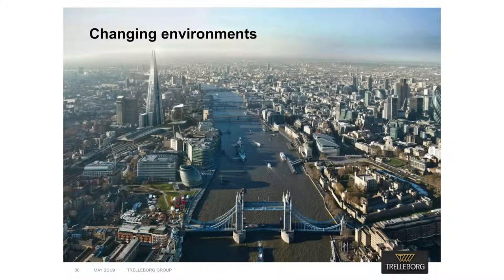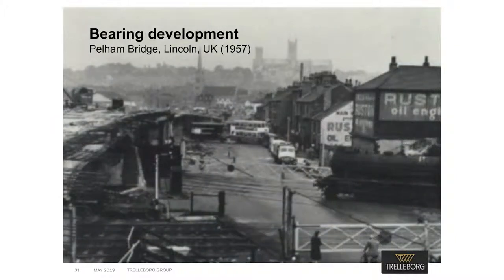Urbanisation and infrastructure will continue to grow, causing ground-borne vibrations to increase. Choosing the correct product and material at the specification stage is vital. A modern building has a design life of typically 60 years or more, so it is essential to test each bearing to verify its stiffness characteristics and structural integrity before it's installed. Once in place, a bearing cannot easily be replaced or rectified. Natural rubber has a proven service life of more than 100 years, and elastomeric bearings are a proven technology dating back to the 19th century.